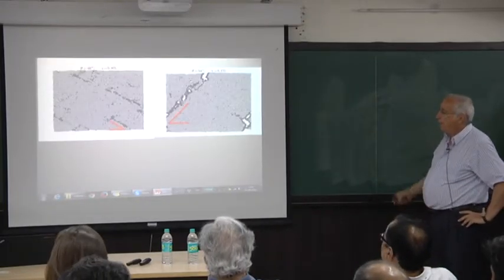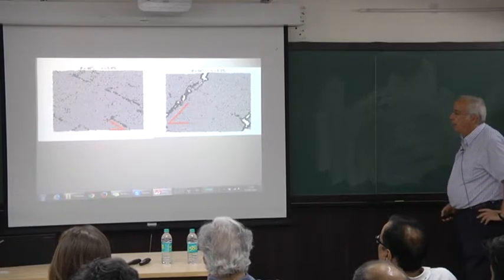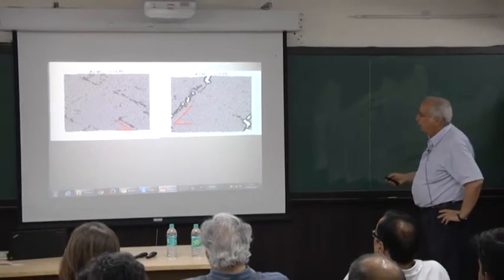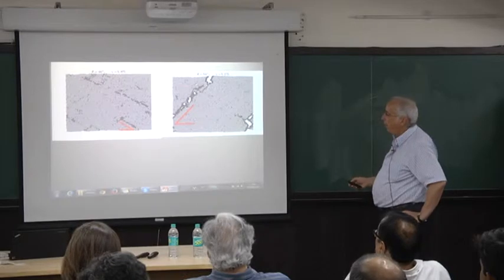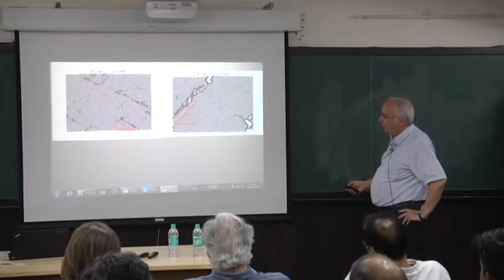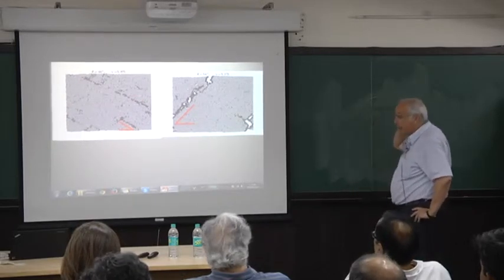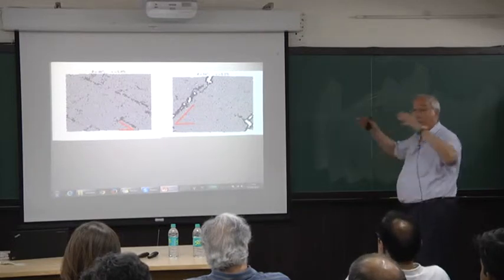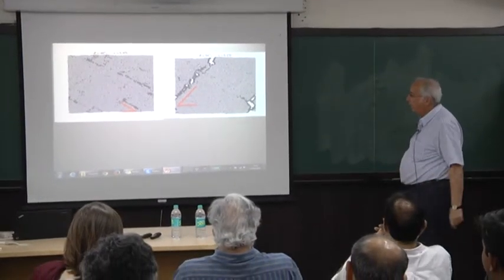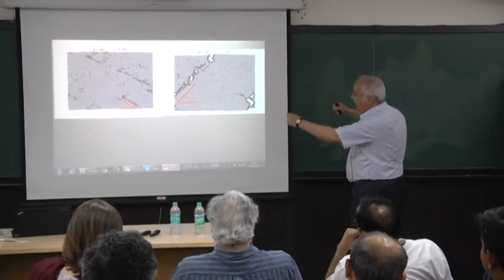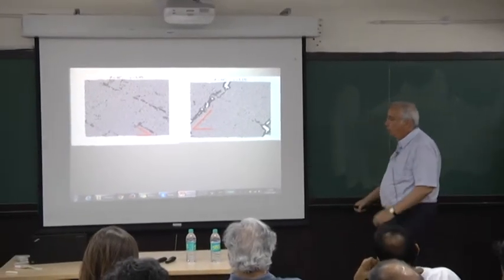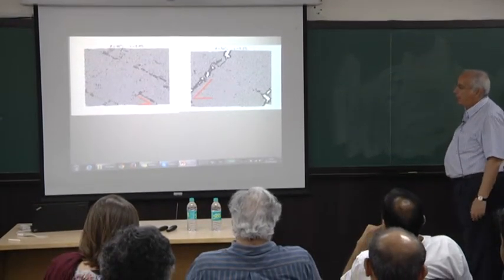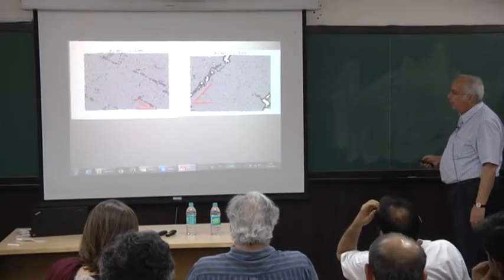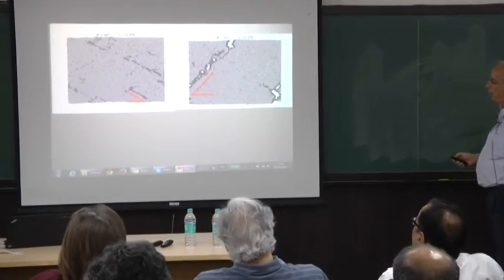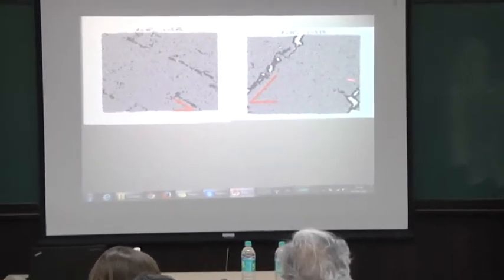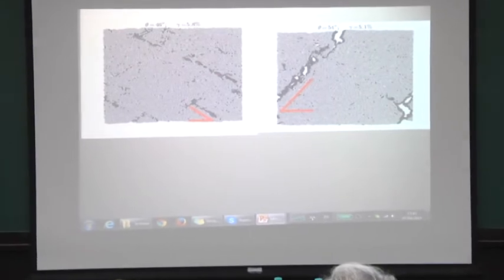Anyway, as I said, the angle. Here are two examples of a glassy material they're going to describe soon. A glassy material that is really binary, as most of these glasses that we looked at in the last couple of days, that are compressed or are being pulled. So it's uniaxial compression and pulling. And as you see, the angle is not 45 here. It's either 54 in this case to the axis, and about 46 here.